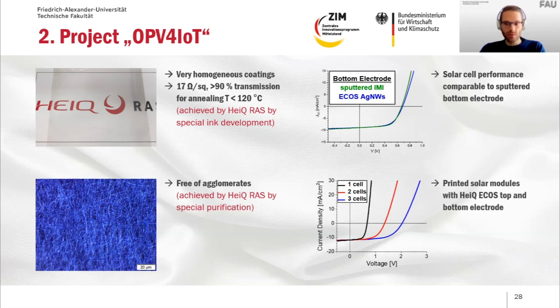And last but not least, we also made modules out of this layer stack with ECOS nanowires as top and bottom electrode, which is actually not too easy because for creating a module, you need to connect several solar cells in series. And the so-called interconnects are the regions where the top and the bottom electrodes come in contact and have to conduct all the current. And if both electrodes are silver nanowires, this contact area is really very low. But we managed to make modules and connect several cells in series with good performance and achieve a good interconnection between silver nanowire top and bottom electrode.